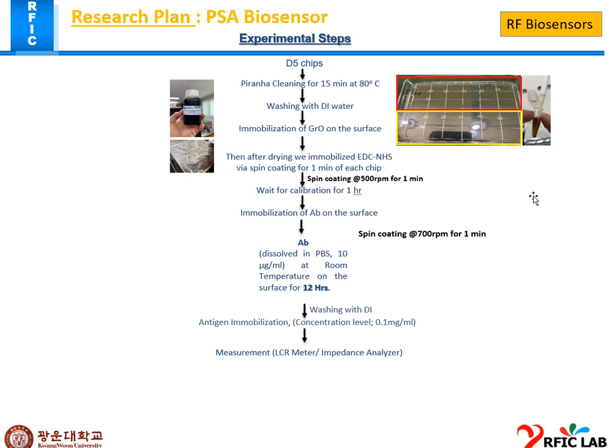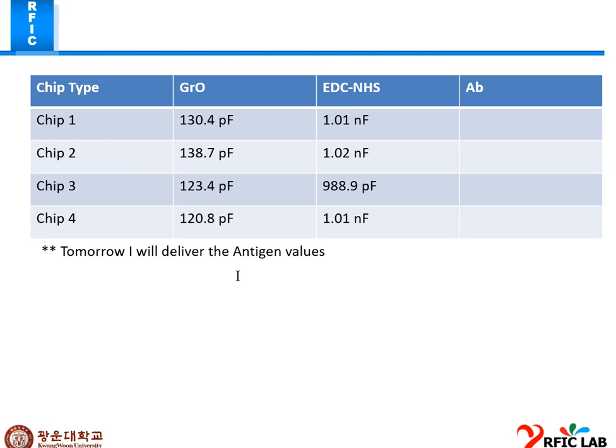So this is the experimental step that I usually follow. As we already know, this recipe is the same as the other PSA antibody antigen. In this condition, we just skip the spin coating method for the following steps; up to the graphene oxide we follow the spin coating, and for the rest of the steps we simply use drop casting, and we got a positive result as well. Now we have taken four different chips, and four D5 chips. At the step of graphene oxide, I got values of 130.4 picofarad, 138, 123, and 120.8 picofarad.